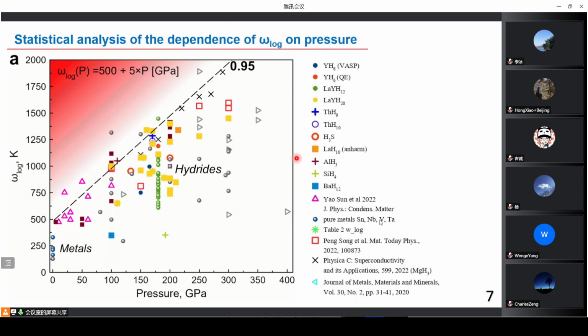Okay, let's start from the statistical analysis of the dependence of logarithmic frequency on pressure. In this presentation, I will mostly use a statistical approach because already a quite huge number of calculations were performed. So we can just analyze them, put a lot of dots on this plot, and see that statistically there is a clear correlation between the pressure and logarithmic frequency in polyhydride materials and even in classical conventional Bardeen-Cooper-Schrieffer superconductors, usually metals and alloys. They're placed at the beginning of this plot.